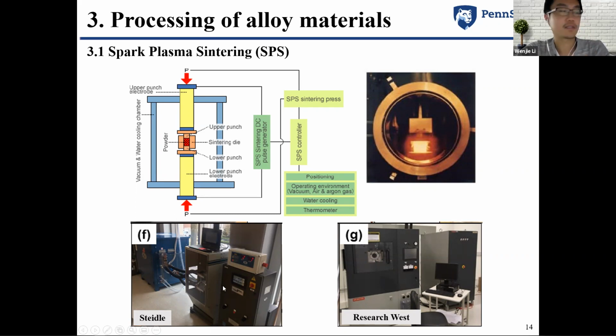One is located at the Steidle building. This is a home-customized, open system. We don't really require a vacuum chamber. We just seal the materials using tight graphite dies. We have some air-sensitive alloy materials, and we never had an issue with any potential oxidation using this equipment. And since we don't need the high vacuum chamber, this is really good for high-throughput synthesis. For sintering, every 15 to 20 minutes we can finish one round and load another one to start.